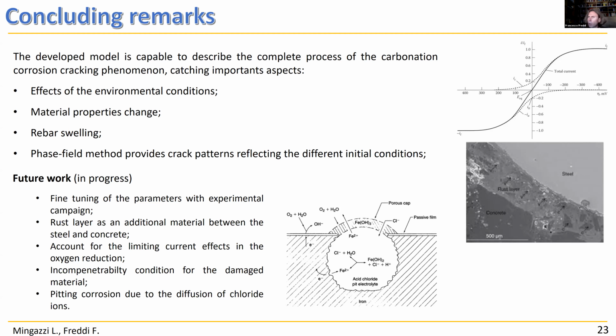I think also from the mechanical point of view, there are some improvements that should be made, because in the model the impenetrability condition is not perfectly fulfilled. So I think there are some crack patterns around the bar that were not so correct from my point of view. And in another direction, which is rather ambitious, another corrosion that is extremely important and dangerous in reinforced concrete structures, especially in pre-stressed concrete structures, is the pitting corrosion due to the diffusion of the chloride ions, because this corrosion is extremely subtle.